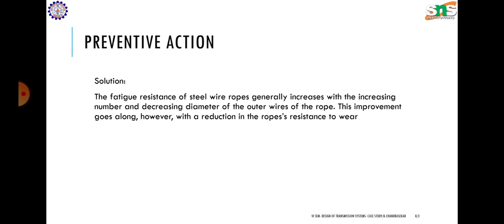So we can prevent this kind of failure, that is, torsion causing fatigue, by increasing the number and decreasing the diameter of the outer wires, and it also improves the resistance to wear. Thank you.